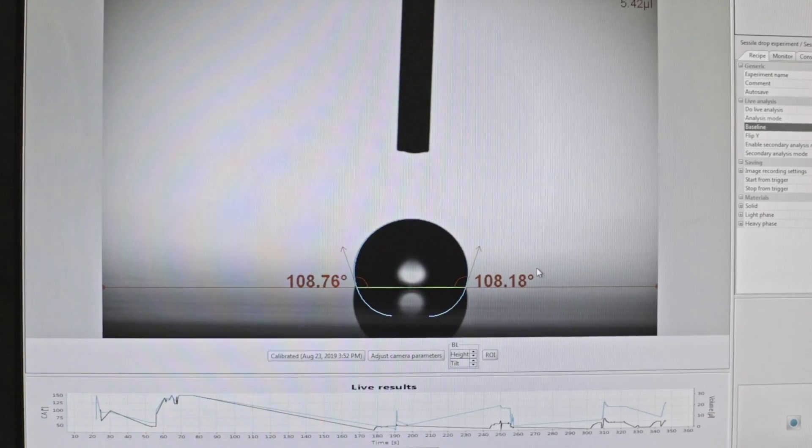What we saw in the lab doing pound-for-pound analysis — make a formula with this resin versus that resin, one for one with no other differences — we did contact angle measurements, scrub testing, coefficient of friction, hardness with pencil hardness tester, pendulum hardness, and impact testing. We saw across-the-board improvements with graphene oxide. While I can't speak to what every other coating manufacturer is doing, that was the natural evolution of our raw materials going through our lab.